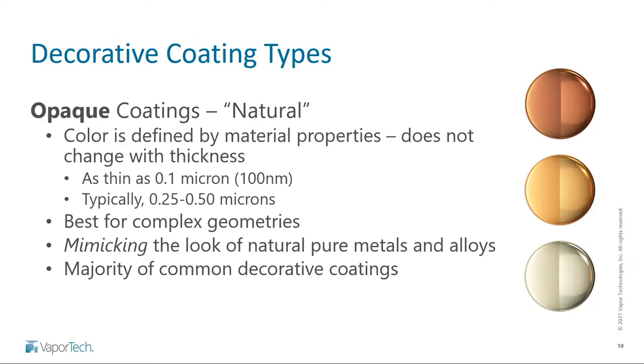You can be a very thin coating and get the same color. You can be as thin as 1/10 of a micron or 100 nanometers, but more often than not, our coatings for decorative tend to be in the 1/4 to 1/2 a micron range, as opposed to, say, thick functional coatings for wear applications, which could be many times this thickness. Because these coatings are opaque, it really works well for complex geometries. If you have parts with a lot of different features and you want to get a uniform color all over it, you really want to work with an opaque coating.